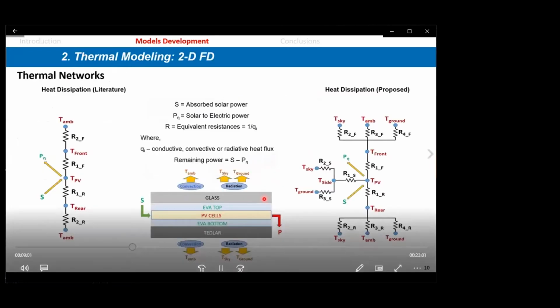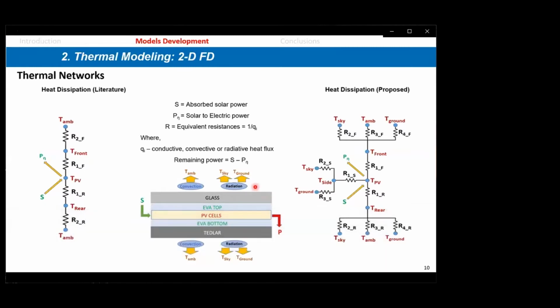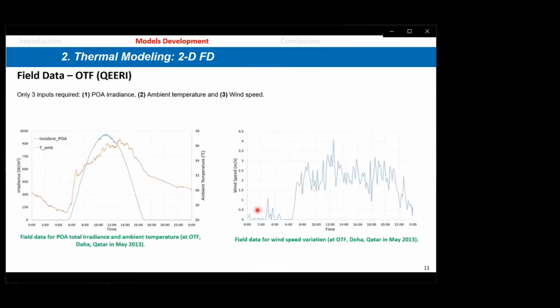Now, the first modification we made is to look at the heat dissipation in the literature, and most of the existing models, or I would say all of them, use this type of schematic here. In fact, this is just to look at the boundary conditions on the top and bottom and the sides of the panel. But when you look at this, we decided that these boundary conditions are not correctly set, particularly the sink temperatures. What we did, we modified. As you can see here, the top sink temperatures are defined differently from the existing model. The bottom as well as the sides. So we included the effect of the sides as well.